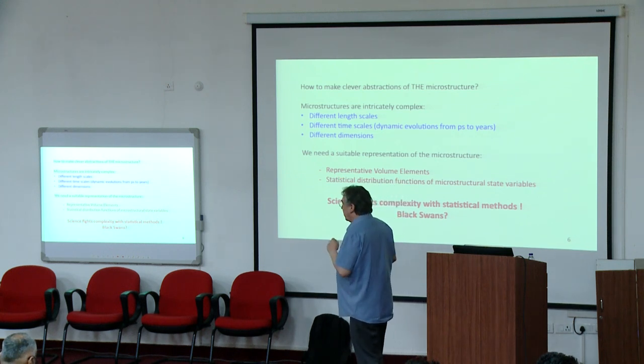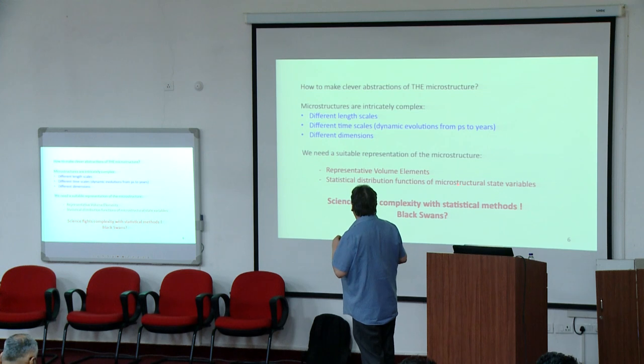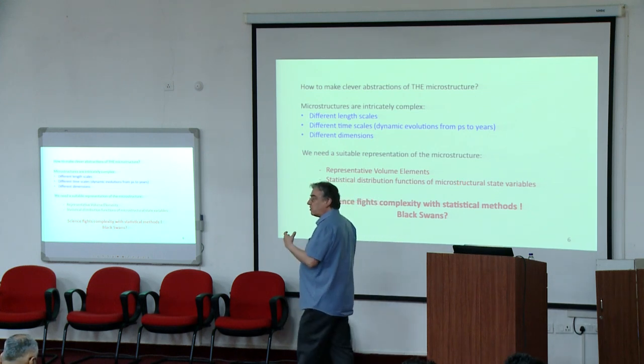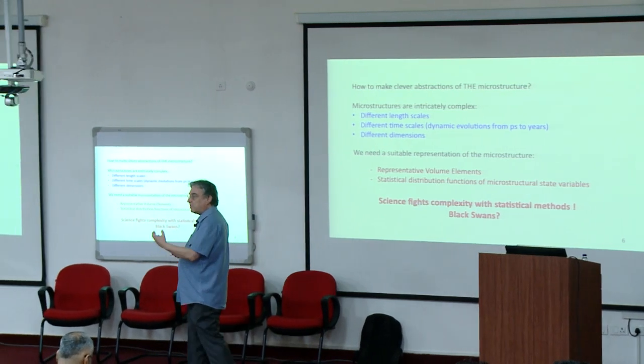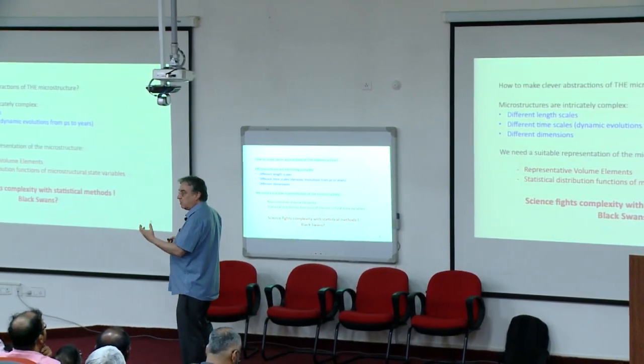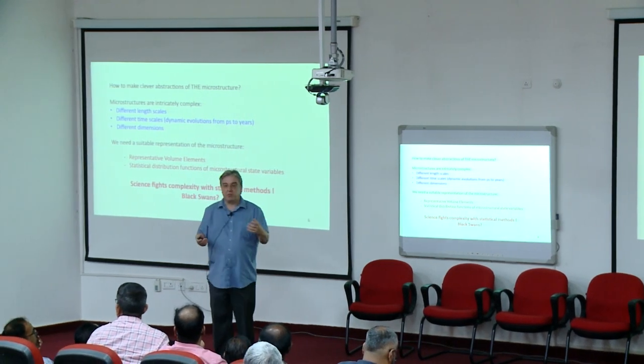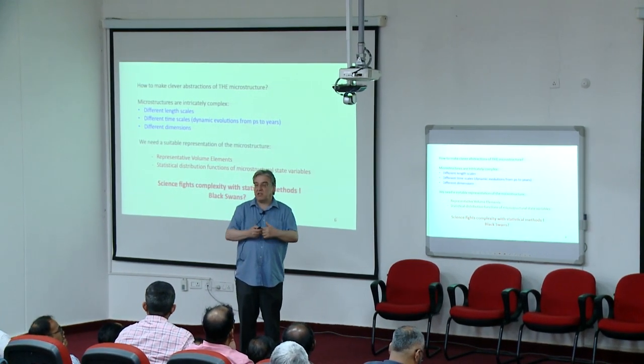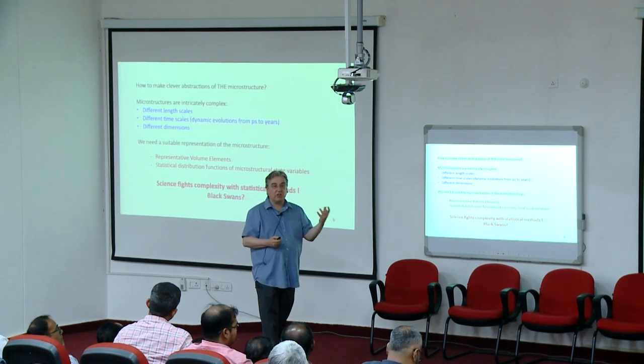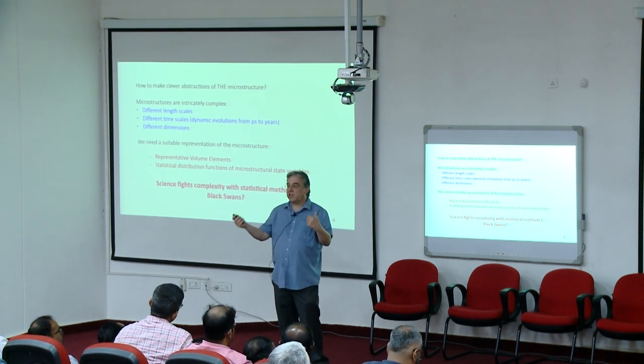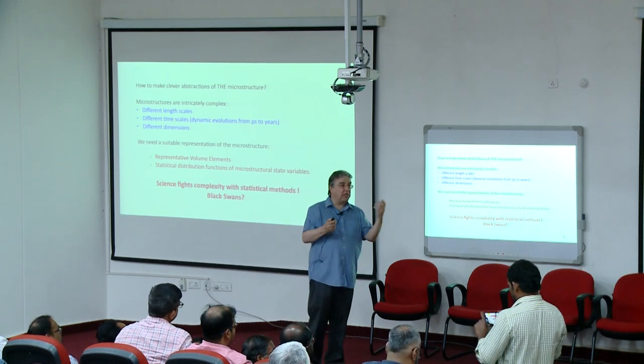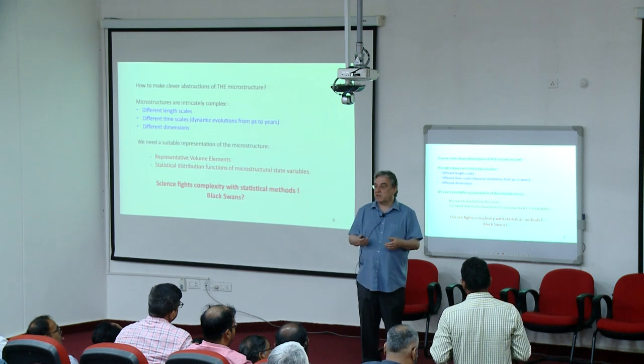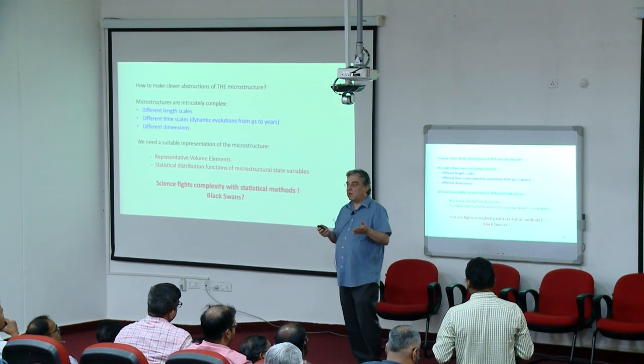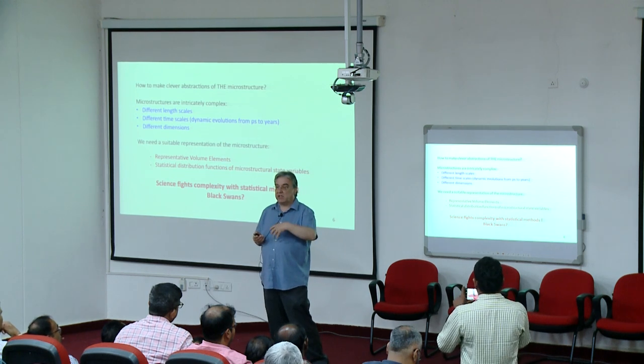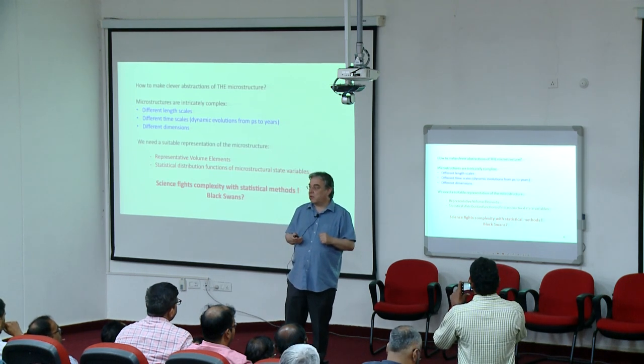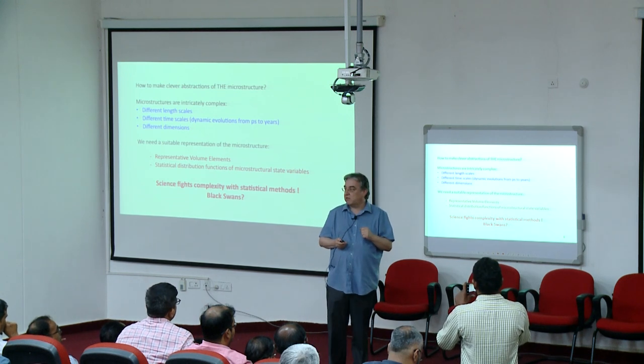Another way of doing this is a statistical distribution function of what we call microstructural state variables. The microstructural state variables are quantities that you relate to the microstructure. For example, the average grain size distribution, or the crystallographic orientation distribution, or the volume fraction of different phases, or the dislocation density distribution. All these are microstructural state variables. The density of solute atoms, carbon atoms in steel, for example.